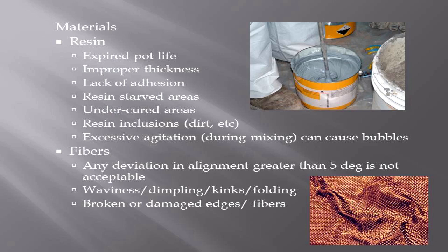The carbon fiber itself, any deviation in alignment greater than 5 degrees in the carbon fiber is not acceptable. Waviness, dimpling, kinks, folding, broken or damaged edges, fibers, it's important to notice. And this is stuff that you can inspect post-construction. You're going to see if there's a kink in that fiber when they installed it.